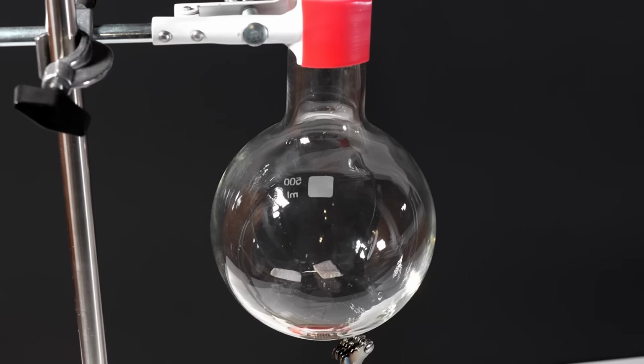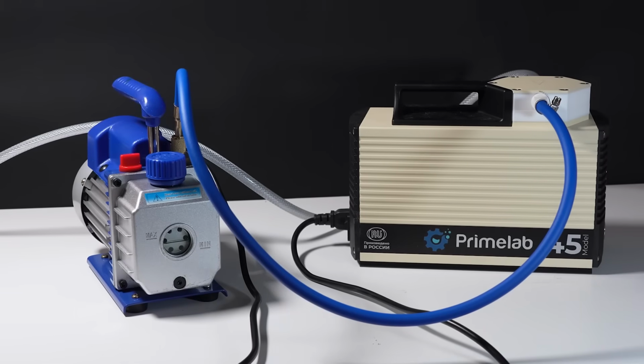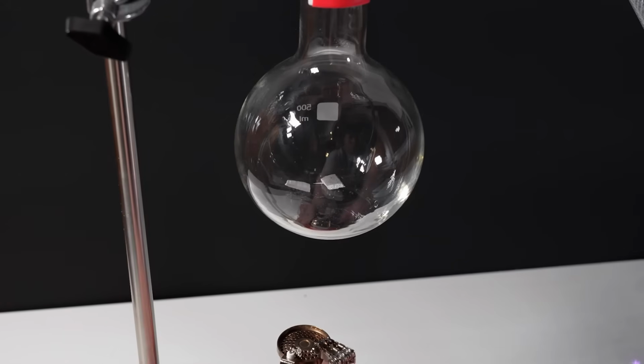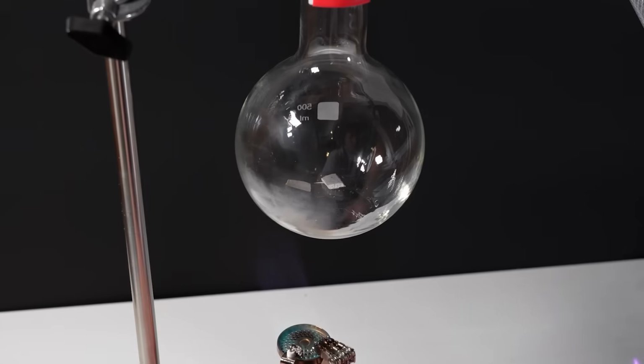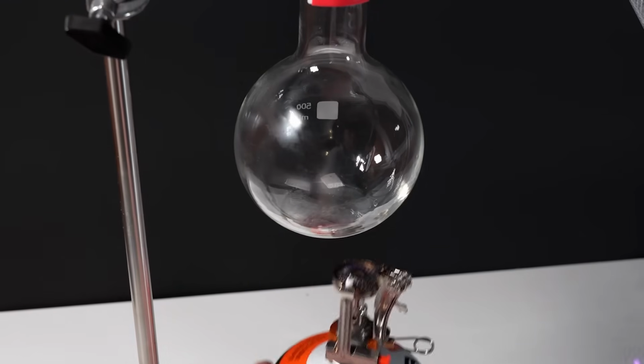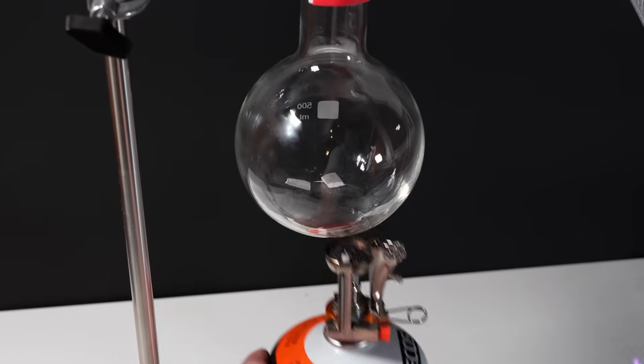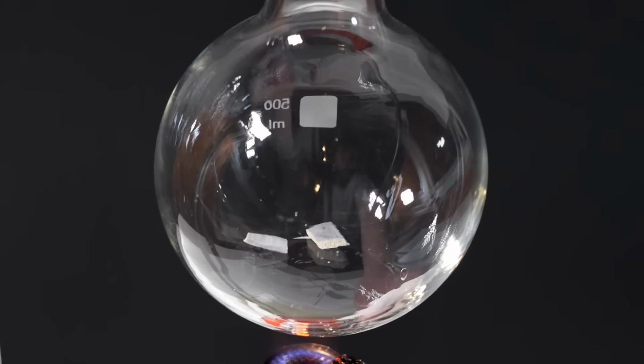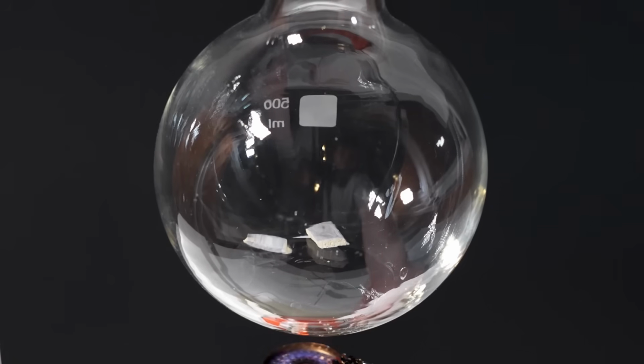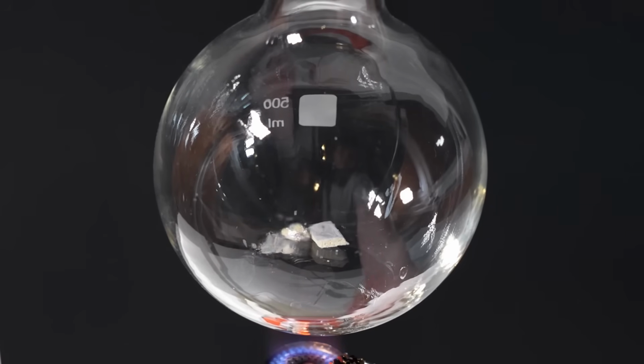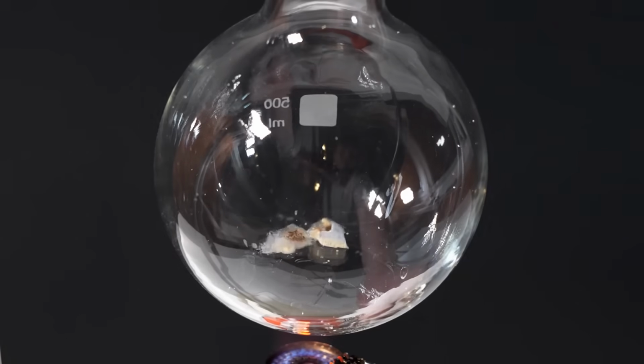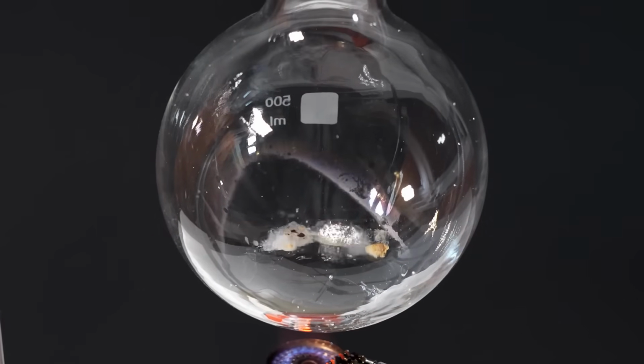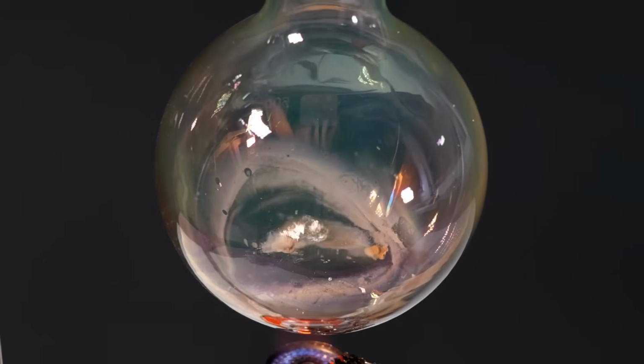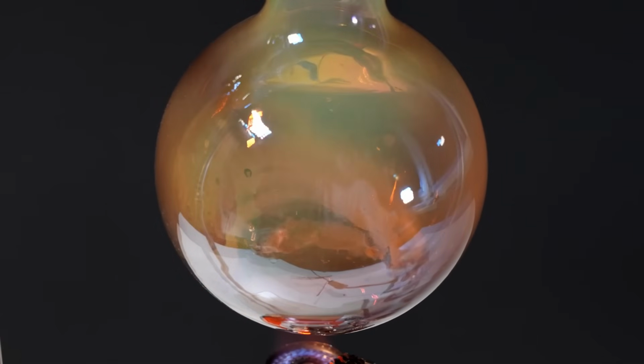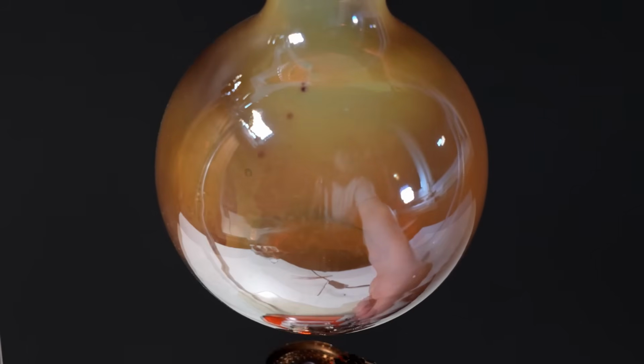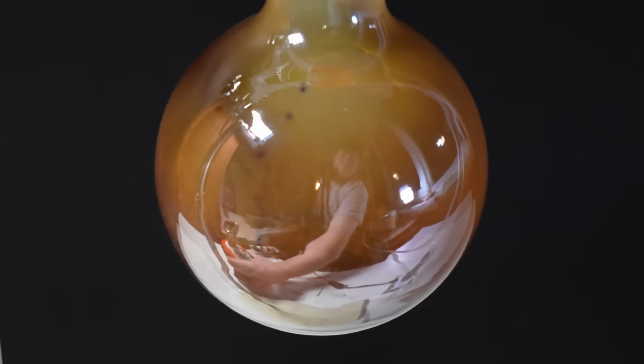Now I start evacuating all the remaining gases from the flask using two vacuum pumps connected in series. This way, the pressure drops faster and reaches a lower level than with one pump. After evacuating the air, I slowly heat the flask with a gas burner so that the sodium melts and begins to boil, since at low pressure it boils at around 300 to 400 degrees Celsius. By the way, this happened quite suddenly, and the piece of sodium turned into a shiny droplet resembling mercury. At that moment, the flask was instantly filled with metallic sodium vapor, which immediately condensed on the cooler wall of the flask, starting to form something like a sodium mirror.